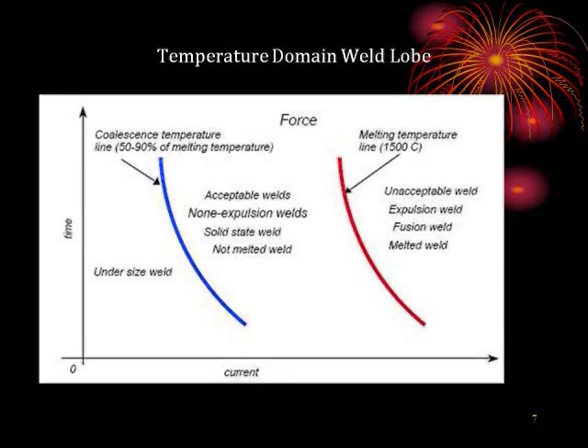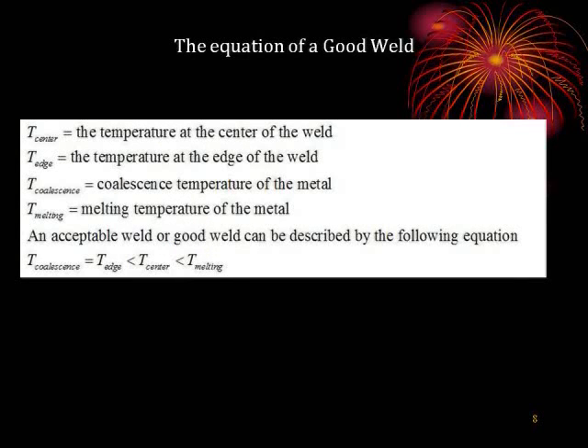By now we know all the acceptable welds are solid state welds. All the expulsion welds are unacceptable welds. From the previous slides, we found out that the weld lobe curves are not time and current domain curves. They are actually temperature domain curves.